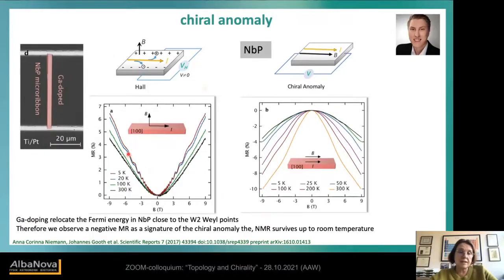So we saw again this quantum oscillation, which allowed us to say where the Fermi energy is relative to the Weyl points, and the small doping made the crystal even better because now we really had the situation that we were very close to the Weyl point. So in transport, we really have to have the Fermi energy close to what we want to measure. Otherwise, we do not see the effect directly. And we did a normal Hall measurement where the magnetic field is perpendicular to the current, and we saw a positive magnetoresistance effect.